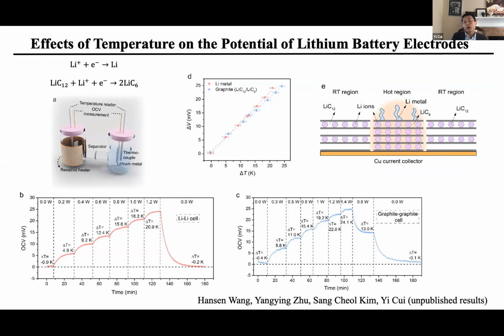What I want to say is if you have a battery, the inside is hot, the outside is cold, particularly under fast charging conditions, it's entirely possible the inside will plate lithium metal, even though the potential, if you think in terms of room temperature, doesn't reach the plating potential, but for the hot temperature, you already do. So that's actually very dangerous.